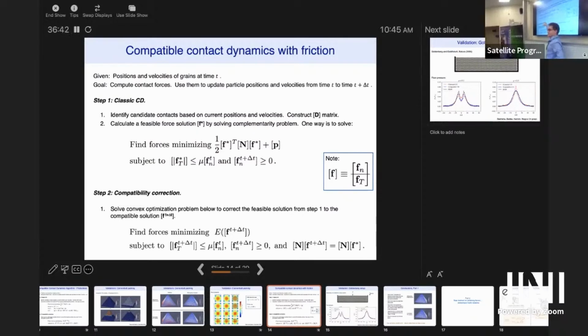Whenever you have inequality bounded optimization, the Lagrange multiplier method becomes the KKT method. It still looks like Lagrange multipliers, but you have slack coefficients. The slack coefficients don't quite work out if you make this the updated normal part. You get what we call normal pollution, where in the condition for the normal force you see some tangential stuff showing up. But if you make this thing right here, which is what I just showed you, it still works quite well and it actually works out perfectly. This will exactly turn right back into DEM with tangential and frictional slip.